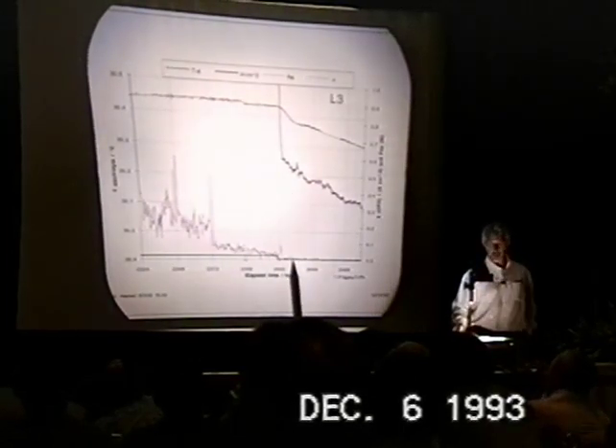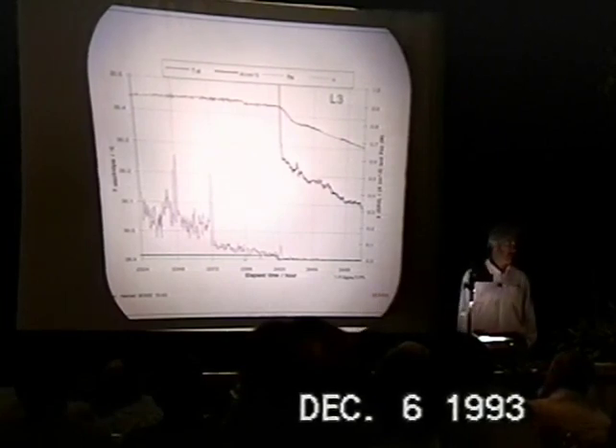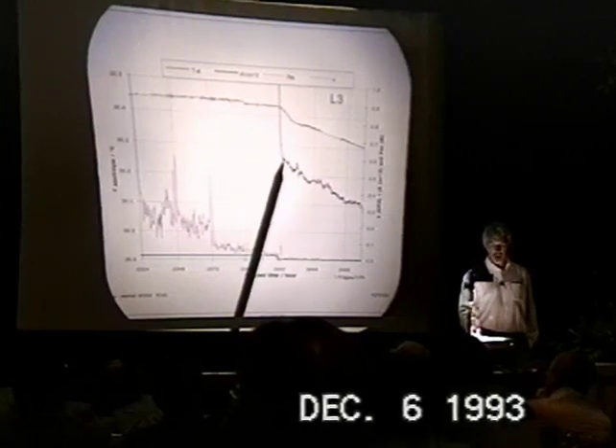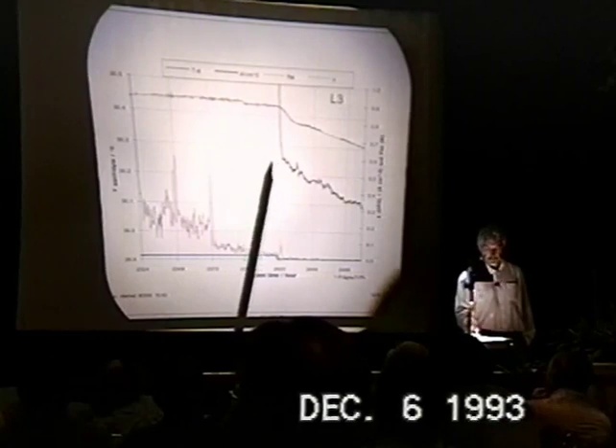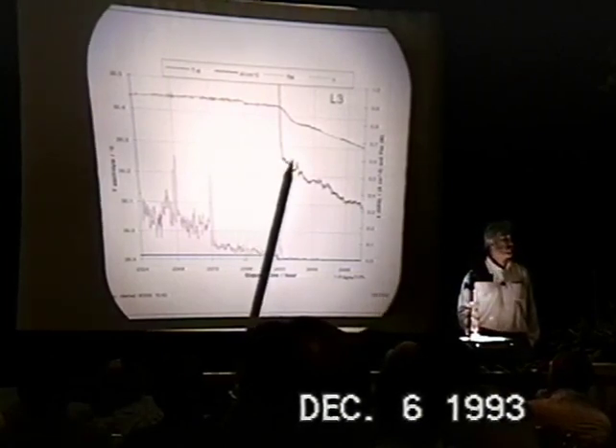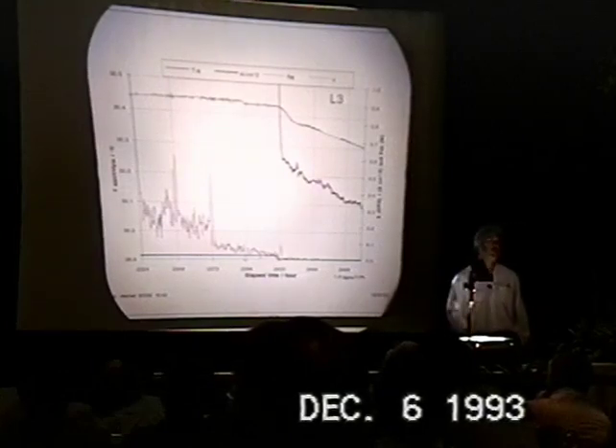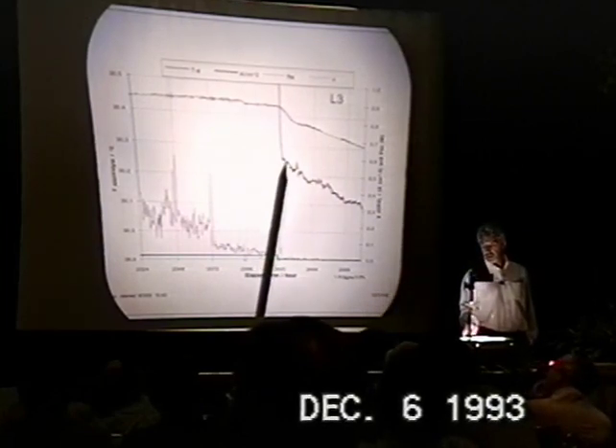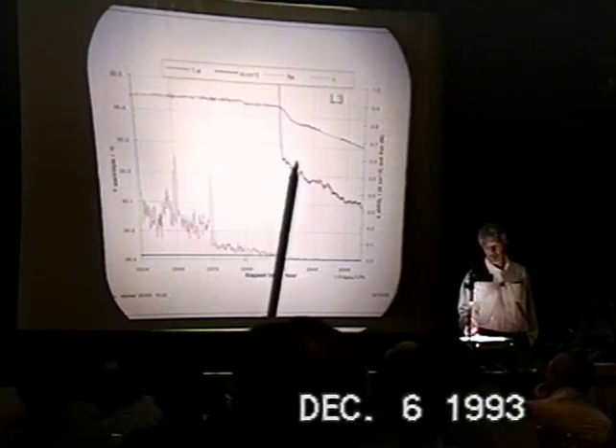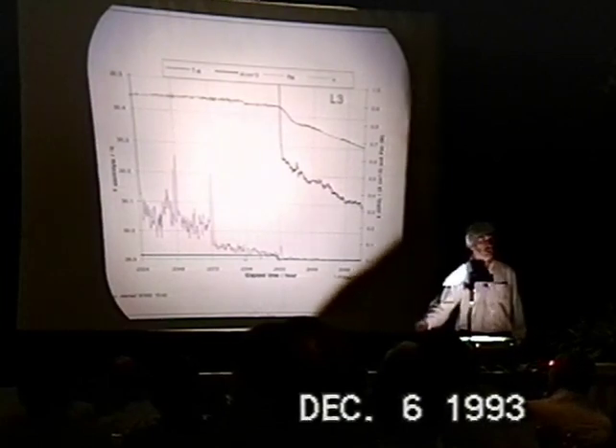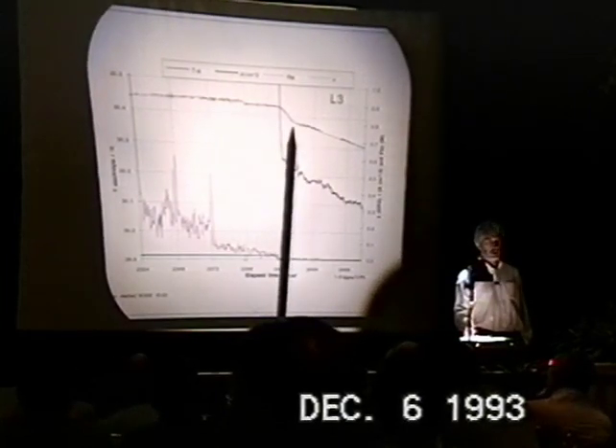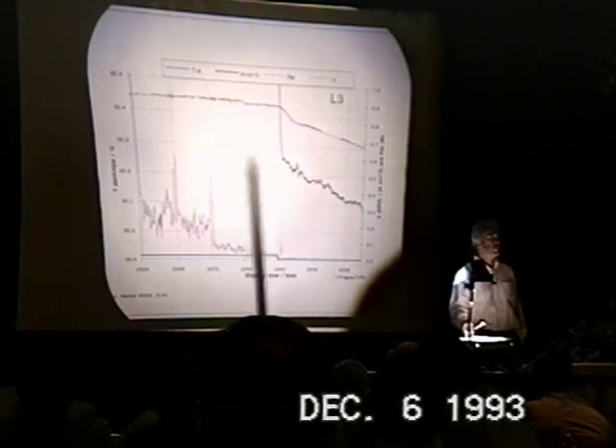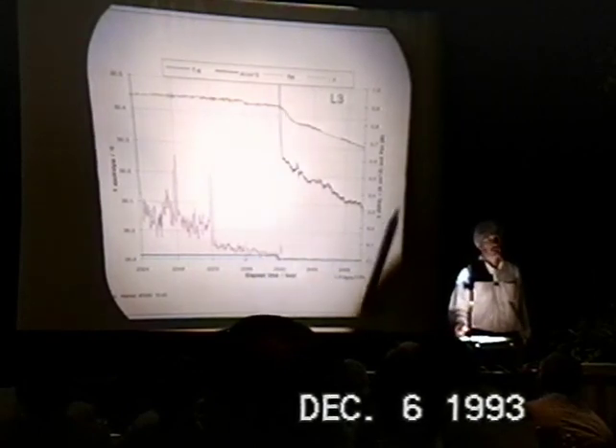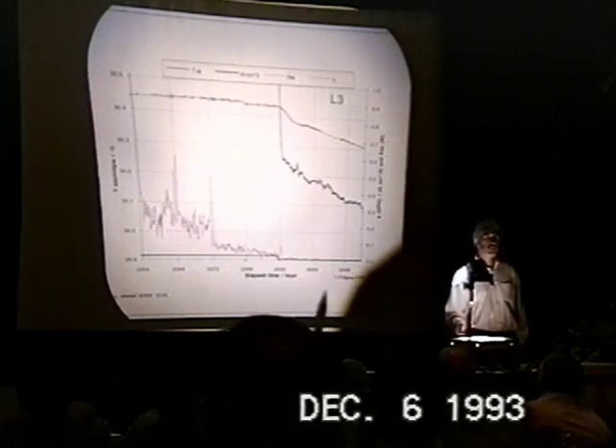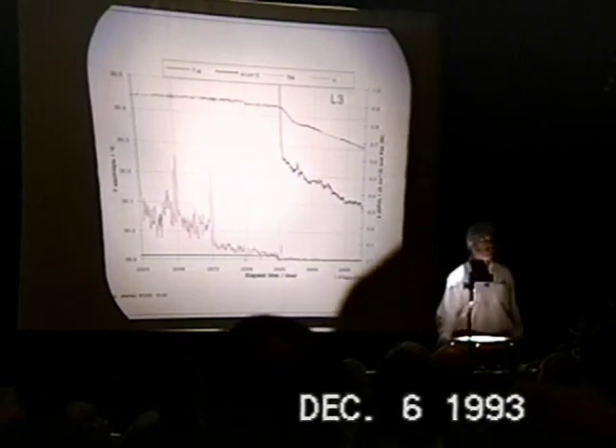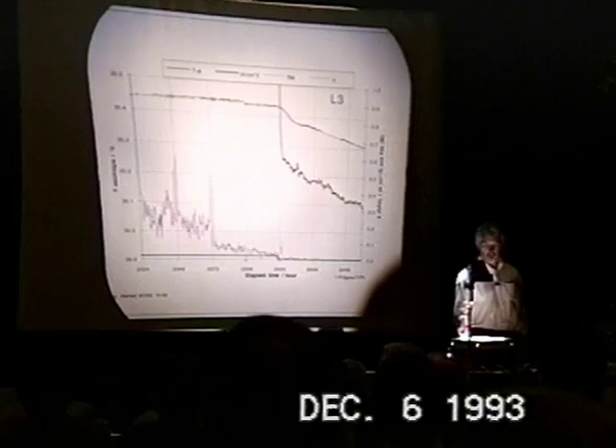The electrolyte temperature sensor comes down. The sensitivity of the calorimeter is such that we can now no longer observe any excess power. It seems to have merged with the baseline. But the cathode electrolyte temperature sensor drops rapidly toward its equilibrium value. This is being bathed continuously in water drawn from the bath at 29.96 degrees centigrade. And yet the electrolyte sensor near the cathode drops and continues to drop over a very, very long period of time, suggesting that even while the cathode is being subjected to an anodic stripping current density, albeit small, and the loading is going down, and a long time after the cell has ever experienced high current densities, there seems to be a residual decrease in the temperature sensed in the vicinity of the cathode.